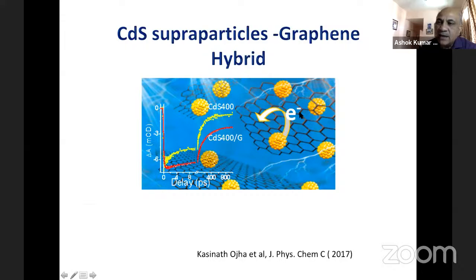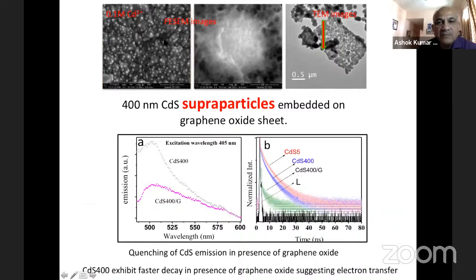What it allows you is higher efficiency of one step in this mechanism, which is electron transfer. And the electron transfer increases very largely in a substrate like graphene oxide, etc. So this is the TEM and FESEM pictures of supraparticles embedded on a graphene oxide sheet. This shows the properties. These are lifetime studies, and you can see that the cadmium sulfide emission gets quenched in the presence of graphene oxide, and the supraparticles, cadmium sulfide 400 means 400 nanometer supraparticles, will decay much faster in the presence of graphene oxide, right?